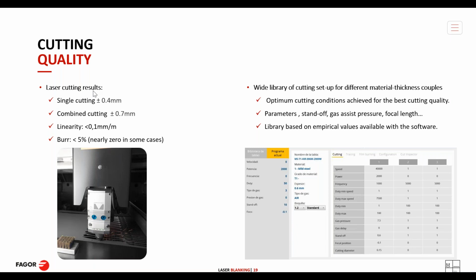As single cutting, we can achieve up to 0.4 millimeters tolerance. These blanks would be cut by a unique laser head. Then by combined cutting, this means in the same piece, the shape has been cut by two or more laser heads. And in this case, the tolerance goes up to 0.7 millimeters. Talking about linearity, the linearity that can be achieved is less than 0.1 millimeters per meter, and the